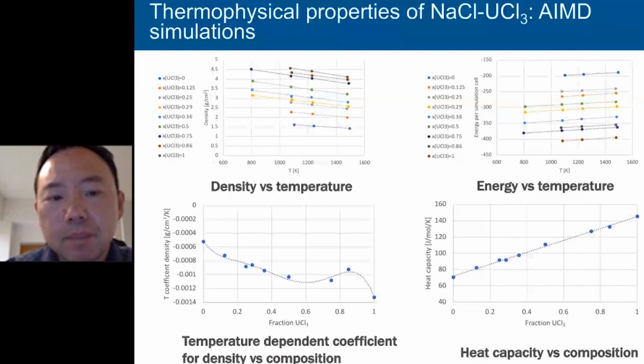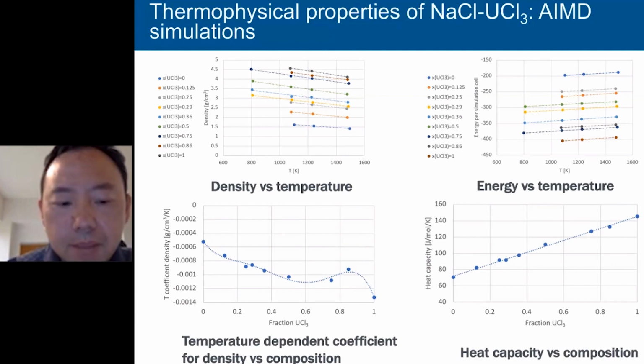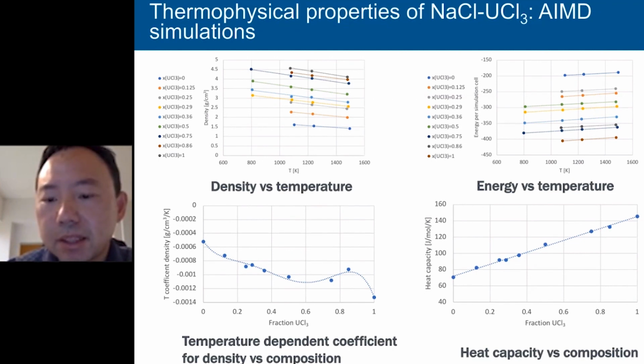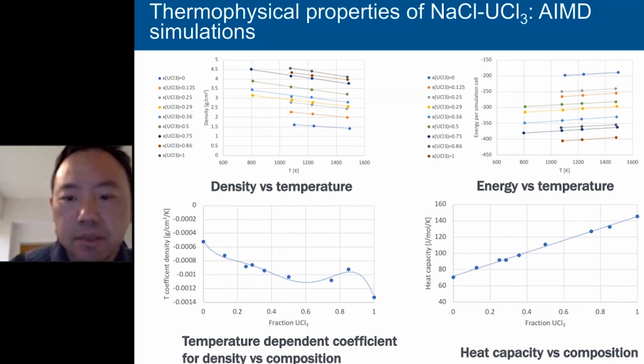Both the temperature dependence of the density and the energy for the many salt compositions David considered in his simulations are shown. All these plots are pretty linear. The lower figure shows the temperature dependent coefficient for density, which actually decreases a little bit with composition, and the right figure shows the heat capacity, which shows a very nice line all the way from sodium chloride to uranium chloride. So this kind of data can be very good for modeling these binary systems.